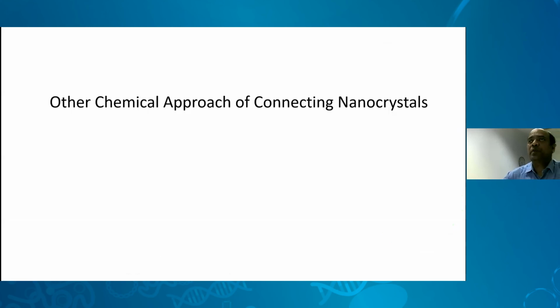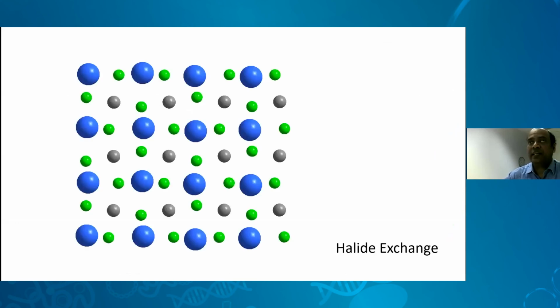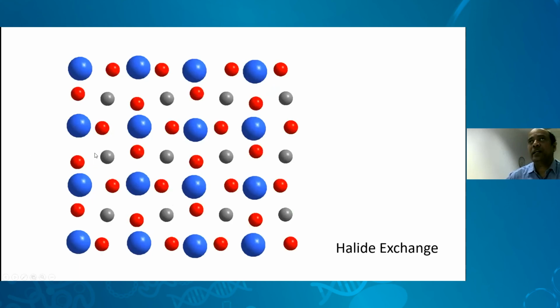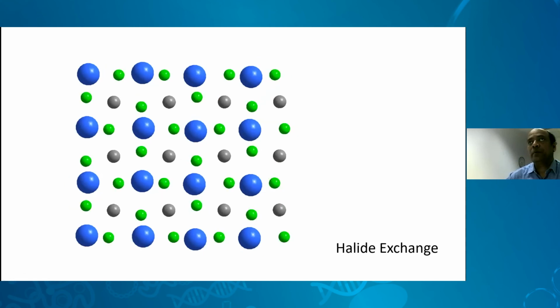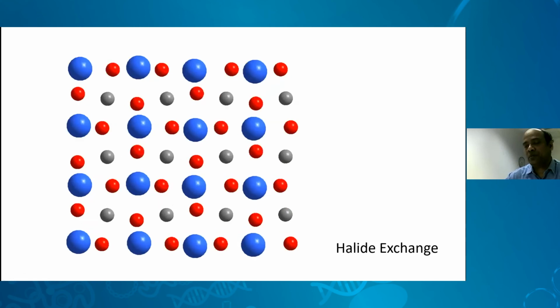There are other chemical approaches for connecting nanocrystals. For example, here I'm talking about halide exchange. You could see here how the atoms are arranged, and the largest, intentionally drawn bigger, is the cesium, which is the blue, and these are the lead, and these are the bromine. If at all we want to do the ion exchange, then the bigger sizes should be in the same positions, or the relative positions should be the same, and the smaller sizes can be on and off. This is similar to what we changed again, bromine to iodine, or it can be done with chloride also.